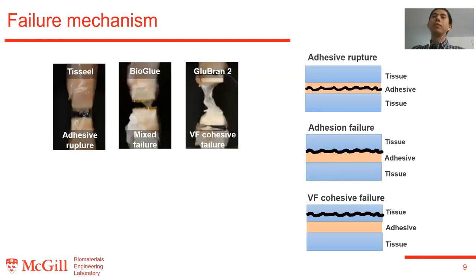Let's look at the failure mode of the commercial products. For Tisseel, although it can form covalent bonding with the tissue, due to the weak and brittle fiber network, the adhesive itself ruptures before the interfacial debonding. For BioGlue, both adhesion failure and cohesive failure of the lamina propria were noticed during the test, which means that the adhesion strength of this product is similar to the toughness of the vocal fold. When we look at the GluBran 2, it was mainly the cohesive failure of the vocal fold. Although the GluBran 2 showed great adhesion, it is stiff and also cytotoxic to the vocal fold, which are big concerns.